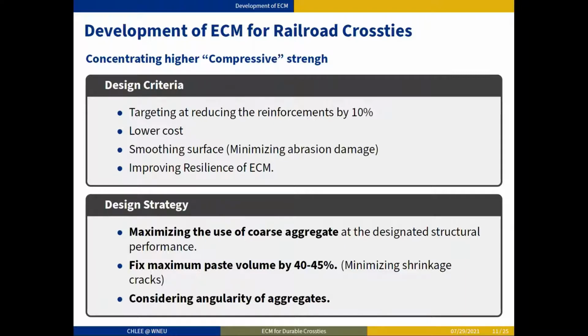To achieve those criteria, we thought about maximizing the use of coarse aggregate to reduce the cost of the concrete, and fixing the maximum paste volume at 40 to 45% to minimize shrinkage cracks as well as reduce the price point. However, those two strategies are not really different from conventional concrete. Therefore, the only factor that we have to carefully consider is how well we design the aggregates. So we thought we need to consider angularity of the aggregates in addition to size and surface area.